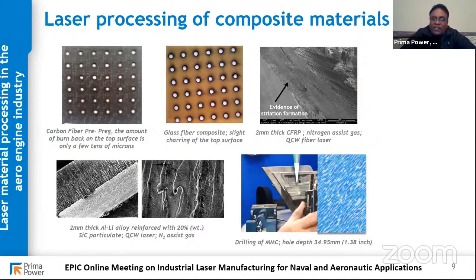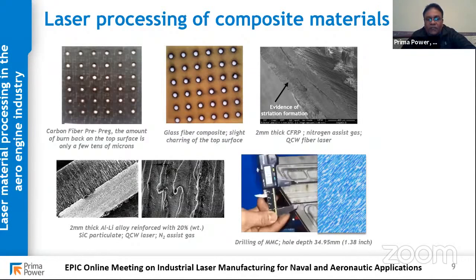So for this one, you can't actually cross section, so we measure the hole taper using a pin gauge. This is about 35 millimeter deep, and now we're going to put a pin gauge through to make sure the hole is quite parallel. So these are some of the things we are currently doing in composites.